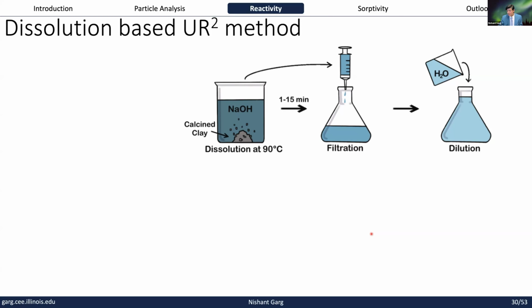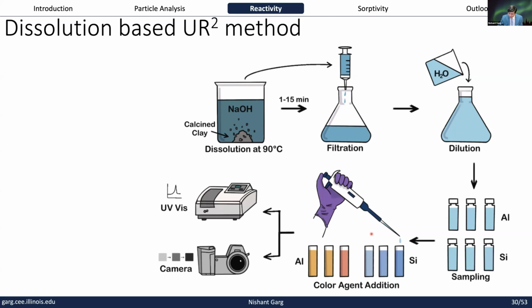And the main effort has been to figure out empirically, under different dissolution conditions at different temperatures and alkalinities, because we don't want to over dissolve a material, or under dissolve. We just want to dissolve the right amount, which is then empirically linked to the 7-day R3 or the 28-day strength. This idea of using dissolution to predict reactivity has actually been around for several decades. For us, the main thing has been to identify the right conditions under which the dissolution approach can work in a very rapid manner, on the order of a few minutes.